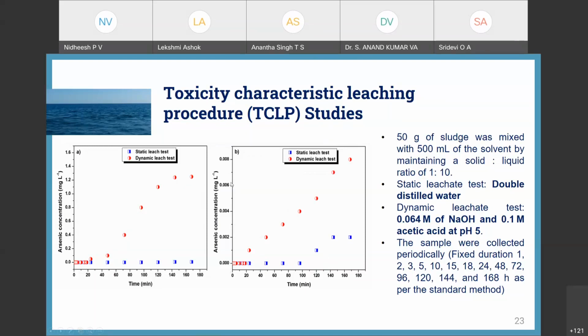Please keep in mind that this is very low compared to this one, because on the axis you can see it is 0 to 1.6 milligram per liter, and here it is 0 to 0.008 milligram per liter. Don't think that the leaching from the concrete is very high. It is very low compared to the original sludge. So that means some arsenic leaching can be arrested by the solidification process.